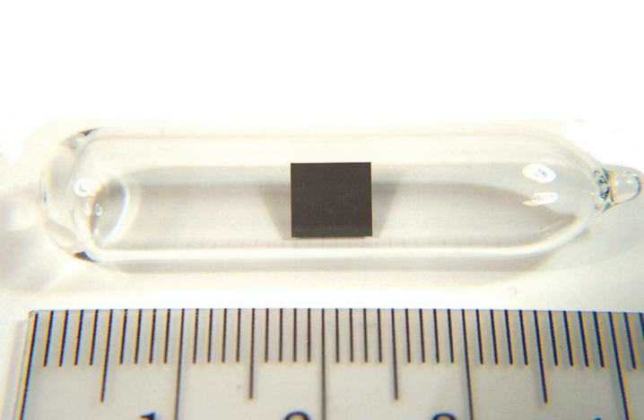The mixture is then cooled to 70 degrees Celsius and diluted with 10 times its volume of cold water, so that any remaining monazite sinks to the bottom while the rare earths and thorium remain in solution. Thorium may then be separated by precipitating it as the phosphate at pH 1.3, since the rare earths do not precipitate until pH 2.